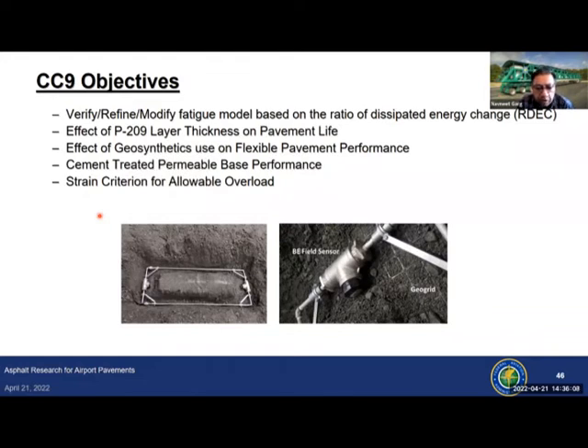For those of you who have used FAARFIELD, you will see that slight changes in P209 layer thickness have a very significant effect on pavement life. And it doesn't make much sense, so we are testing it out with full-scale tests in CC9. Then we are looking at the effect of geosynthetics used on flexible pavement performance, because in our previous test cycles, before our subgrade failed, we had failure in our sub-base layers, because, you know, unbound aggregates cannot take any tensile stresses. And basically you see those materials separate and you see subgrade intrusion into the subbase, and that's when your subgrade failure starts. So we are using geosynthetics to see how it affects that failure mode.